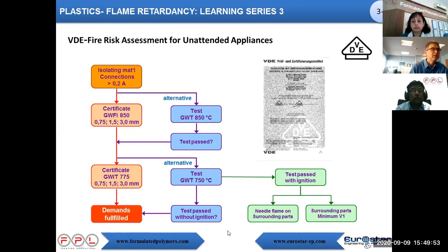In the case you cannot survive a test on 750, then you have another route where you can pass the so-called needle flame test. The needle flame test is a simplification of a UL test. The flame is very tiny, and you are applying it for 30 seconds. But basically, it's almost a burning test. And another way would be to make sure that all the surrounding parts are minimum UL 94 V1.